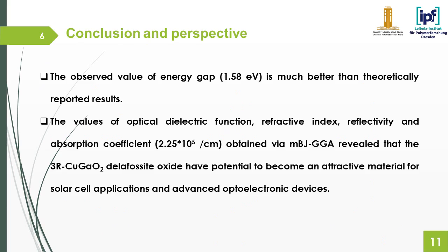In summary, the obtained value of the energy gap is much better than the results obtained theoretically. To the best of our knowledge, there is no experimental data concerning this delafossite oxide considered in this study. As well, the values of the optical dielectric function, refractive index, reflectivity, and absorption coefficient obtained within the modified Becke-Johnson potential show that our delafossite oxide has the potential to become an attractive material for solar cell applications and advanced optoelectronic devices.